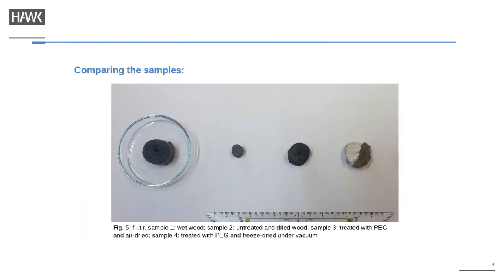To illustrate this, I have four samples. This used to be one piece of branch, which I cut into four pieces, all of the same size in diameter as well as in height. The first sample shows an untreated waterlogged object, which is still wet and has a really spongy texture, is dark in color, as you can see, and heavy because of the weight of the water. Sample two shows an untreated piece of waterlogged wood that was just left to be air dried. You can see that it completely lost its size and shape.